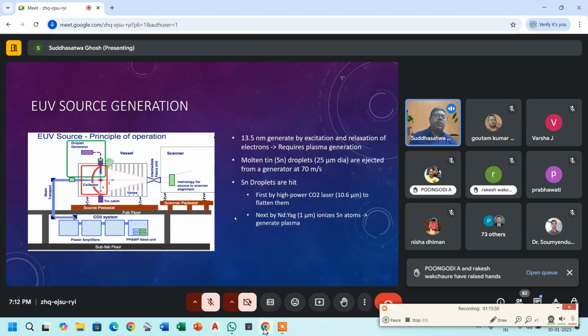There was a bigger challenge to come up with an EUV source. In the past, I've mentioned that we used laser sources like 193 nanometers and 248 nanometers, but making a source for EUV specifically was in itself a challenge. There was no source available when this project began 20 years back. So ASML came up with a new source generation, and how it is generated is quite interesting. The 13.5 nanometer light is generated by excitation and relaxation of electrons, and it needs plasma generation to generate the source.